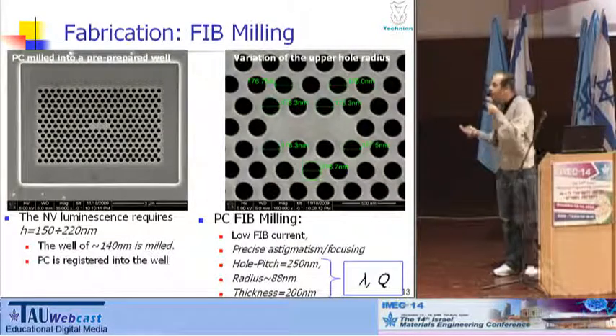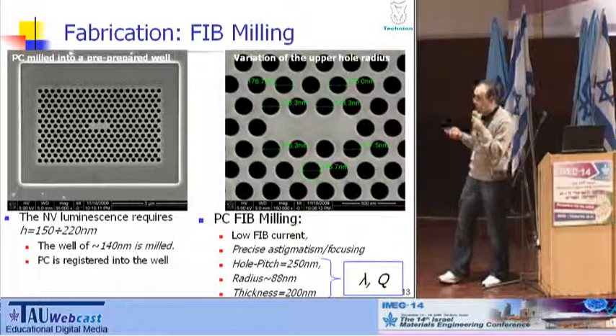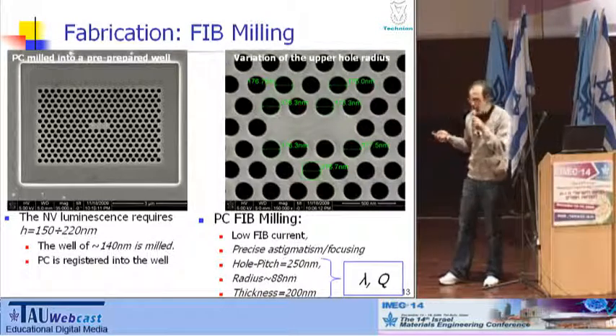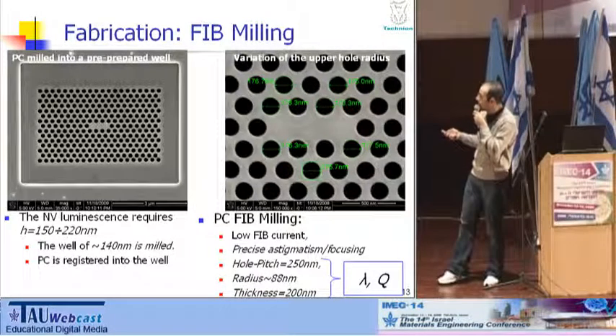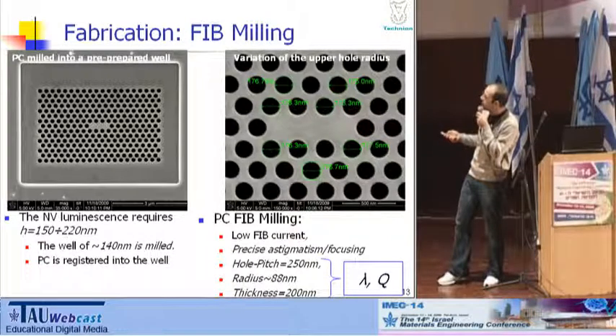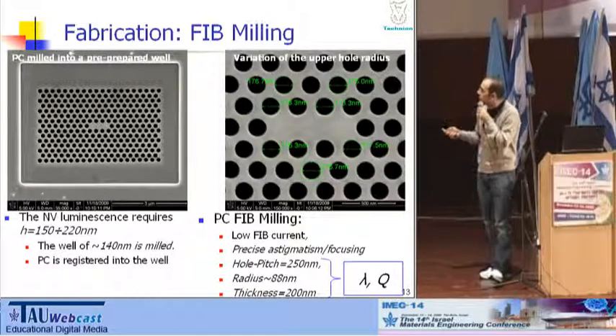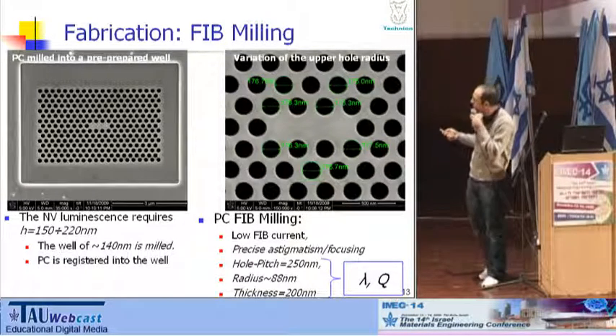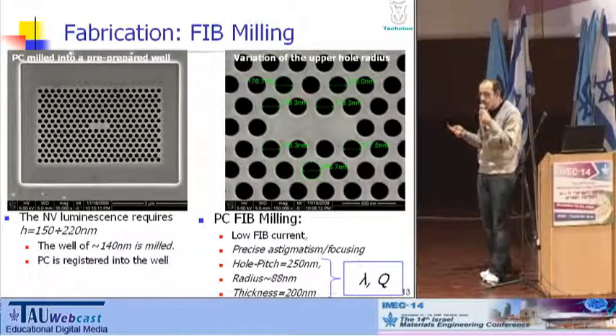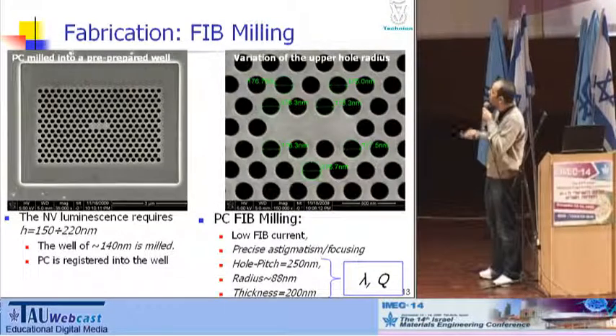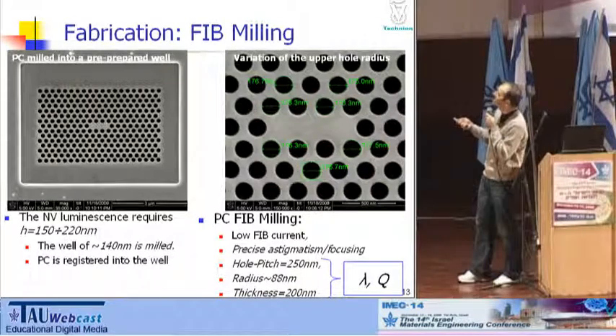Now, in order that the cavity would operate in the visible region, which is the photoluminescence of the NV defect, we've got to make the thickness 150 to 220 nanometer. So we milled a well with focused ion beam, and into this well we have produced the photonic crystal cavity, which is a 3 missing hole cavity.